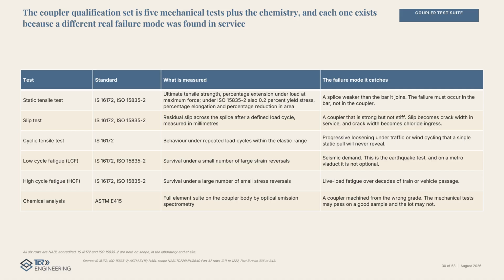The coupler qualification set is 5 mechanical tests plus the chemistry, and each one exists because a different real failure mode was found in service. The static tensile test proves the splice is stronger than the bar, so failure occurs in the bar. The slip test measures residual movement across the splice, because a coupler that is strong but not stiff turns slip into crack width, and crack width into chloride ingress.